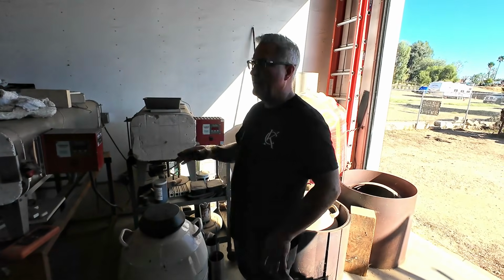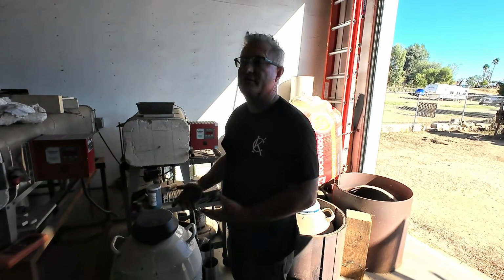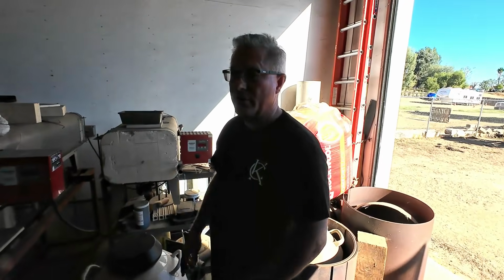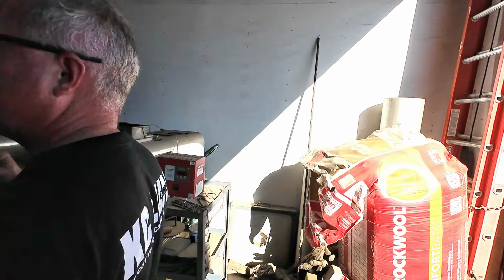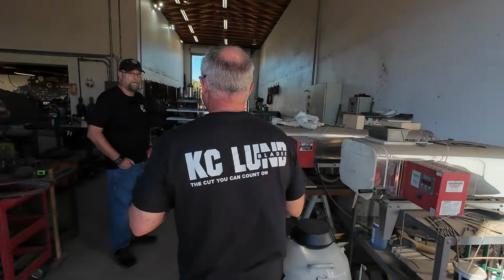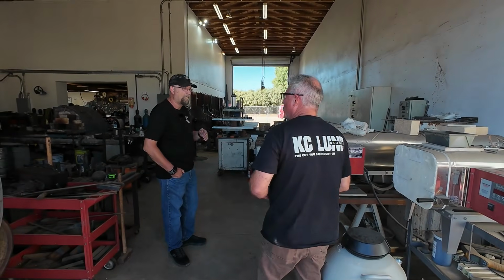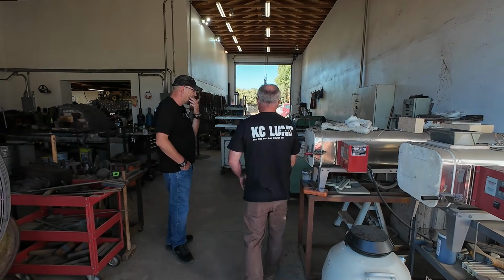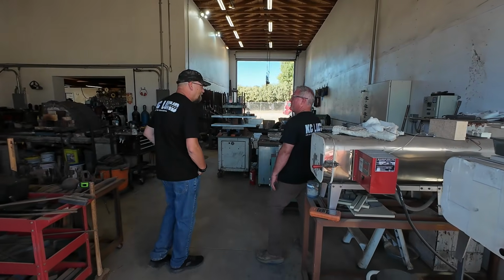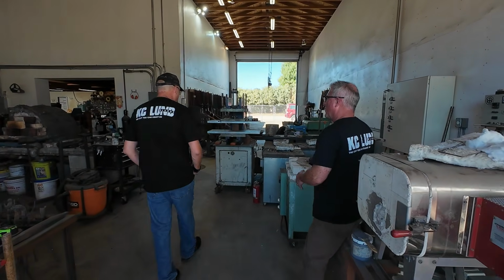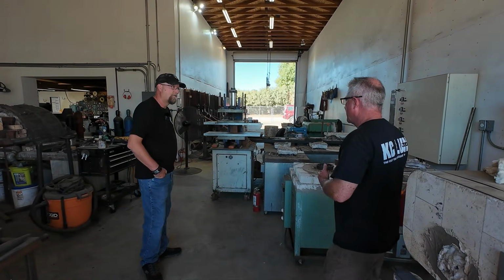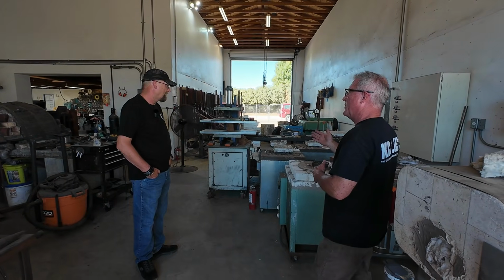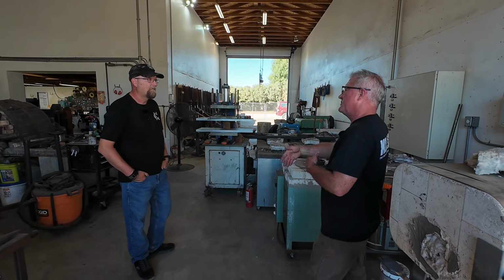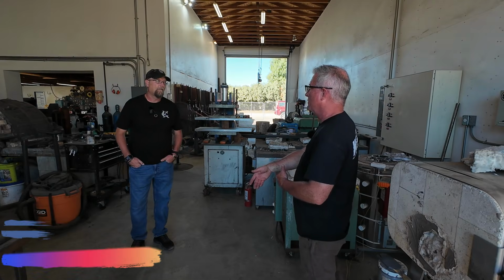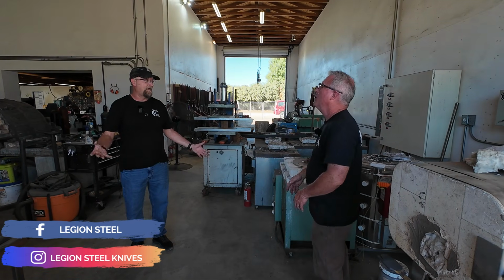So you get absolutely clean blades. They come out, they look like they've been blued. There might be a little oxidation on them, not much, more like a cold blue process. So you get nice clean blades, very stress-free when you're hardening them, which is better because salt skips the vapor barrier. When you quench something into, say, water or brine, which is salty, you get that steam layer around it.